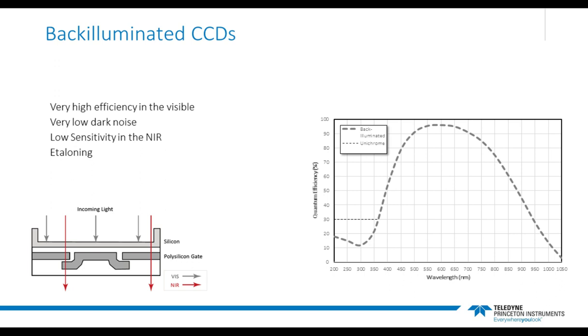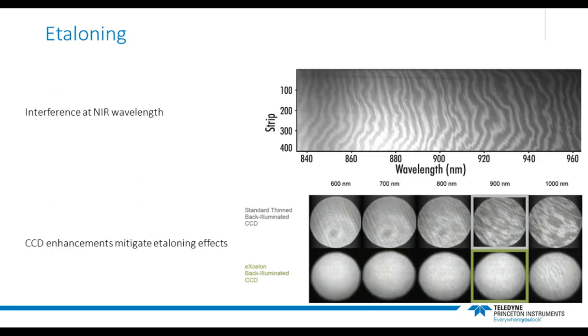The light-sensitive region in these devices is etched and polished down to a very low thickness, so about 13 micrometers. So that means although the efficiency in the visible is high, the sensitivity in the NIR typically rapidly decreases as the mean free path for absorption of photons increases with the wavelength. So they just pass through the material. The longer mean free path can also lead to interference due to multiple reflections of light on the front and back side of these sensors.